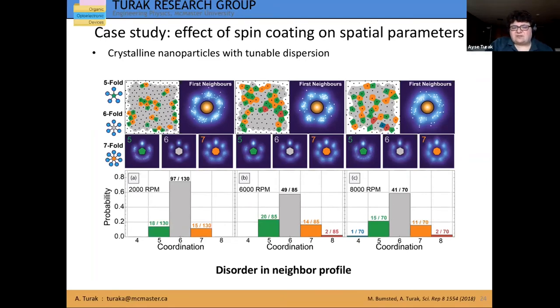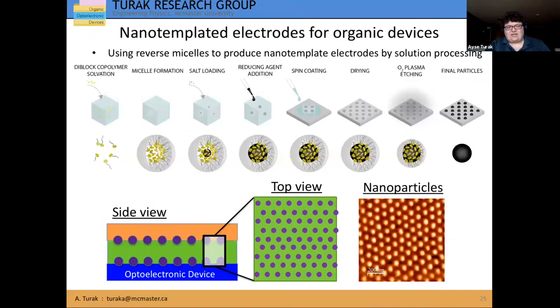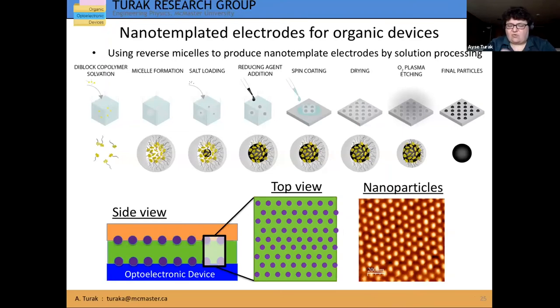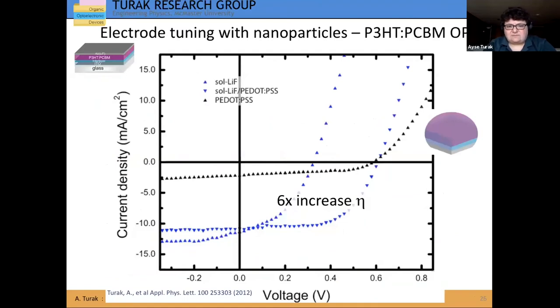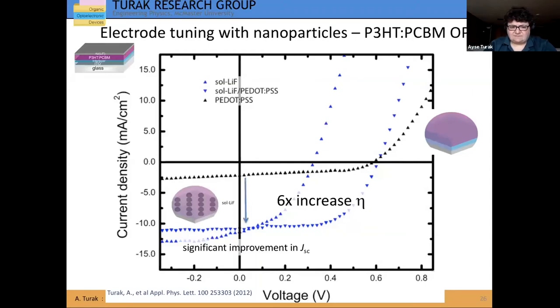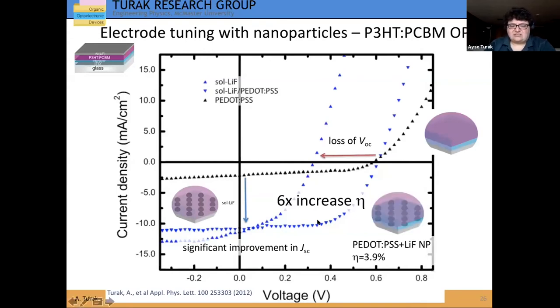These are the tools that we started out with. We were very interested in making nanotemplated electrodes to see if we could impact organic devices — producing an ordered array versus a disordered array to see the impacts of that, and the size and all these different kinds of things. We incorporated them into organic solar cells using very standard P3HT-PCBM structures. And we were able to, by introducing our nanoparticles, increase the short circuit current — which was accompanied unfortunately by a loss of the VOC — but by tuning the transport layer, we could actually see a six times increase of the efficiency, just through tuning the interface using these nanoparticles.